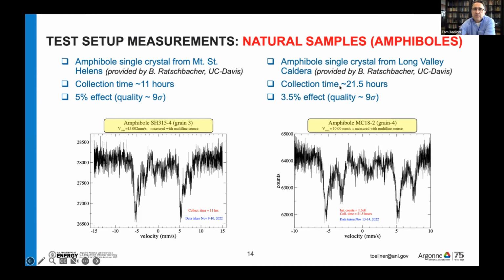The other amphibole is from the Long Valley caldera out in California. And we measured that for almost a day. This is a very low iron concentration, a 3.5% effect here. 3.5% effect, that's the magnitude of the dip relative to the baseline. And again, the quality is about the same, measured in 21 hours. And so this is what you would expect in about 21 minutes with the new instrument.